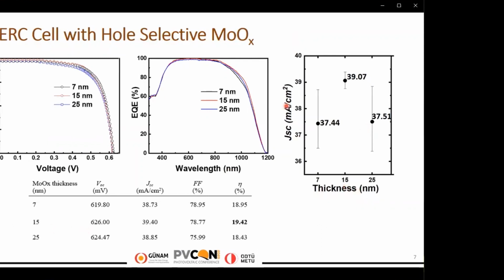And PERC with 15 nanometer molybdenum oxide shows better EQ response in the infrared, as shown in the figure in the middle, indicating superior carrier collection in this region as compared to the 7 and 25 nanometer. And EQ response translates into improved overall JSC, as seen here in this graph.